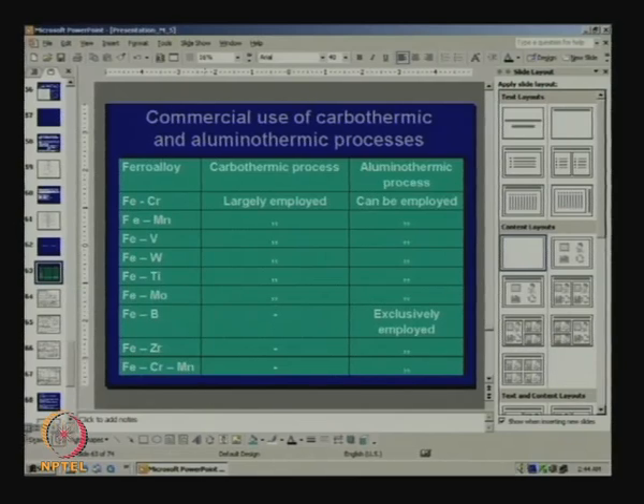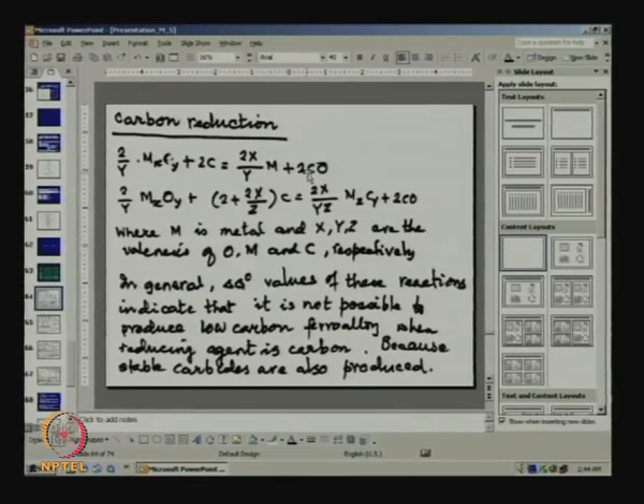Okay. So, we were here, and I have mentioned that the aluminothermic process seems to be applicable universally, whereas the carbothermic process would be largely employed for some, but not exclusively. Now, let us do a bit of thermodynamic analysis. Suppose we have a metal oxide MxOy, and we want to reduce it by carbon. Depending on the temperature, you produce either CO or CO2. Let us assume we are going to fairly high temperatures, because these ferroalloying elements form stable oxides. So, we will produce CO.